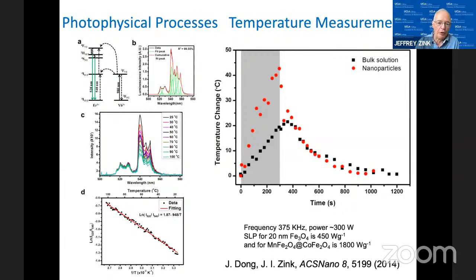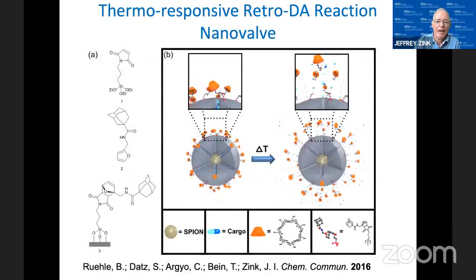So we were able to show that we're getting heating. Of course, the operation of polymers and other caps in the presence of the heat also proves that the systems are heating up. That's how we can measure the temperature. So now we have an idea on how much we can do. The final step is to use a thermal responsive cap to be able to cap and release. And we have a variety of these sorts of caps that can be used.